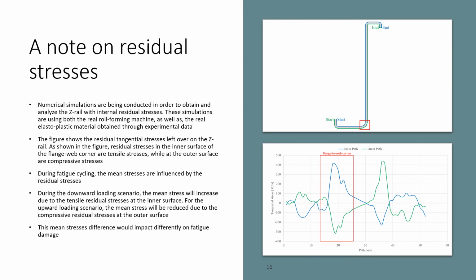Now we can see here in green, the path is going to pass through the outer surface of this corner, while the blue path is going to pass through the inner surface of the corner. Here on this graph below, we have the tangential residual stresses left over from the fabrication process. You can see here in blue, the inner path, we have tensile stresses, while in green, at the outer path of the corner, we have compressive residual stresses. So what does this mean?